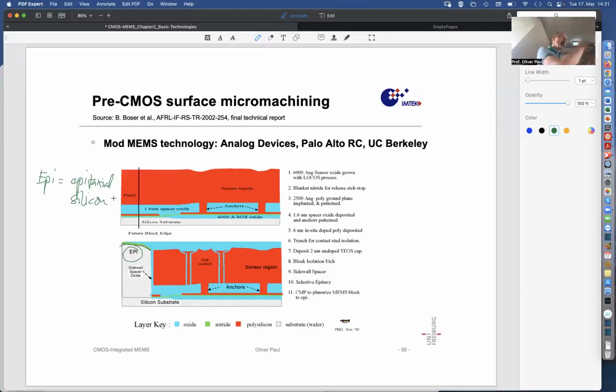And then the silicon condenses, adheres, adsorbs on the surface, migrates to positions where it feels comfortable, that is in crystalline positions, with tetrahedral bonding. And then the silicon grows layer by layer to the thickness of what was added at the beginning in micromechanical structures. So epitaxial silicon is grown at let's say 1,200 degrees centigrade, 1,100 degrees centigrade. There's different temperatures, but it's high temperatures to have high growth rates.